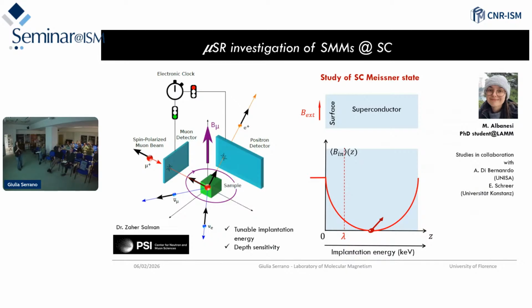Another thing that we have recently done is to ask ourselves if the single molecule magnet, other than being just a probe for the superconductivity, can somehow influence the superconductor. To do so, we went to the muon facility in Switzerland, in which we could hit the sample with a muon, and the muon, in its decay inside the bulk of the sample, emits a positron roughly in the direction of the spin moment it encounters within the sample.